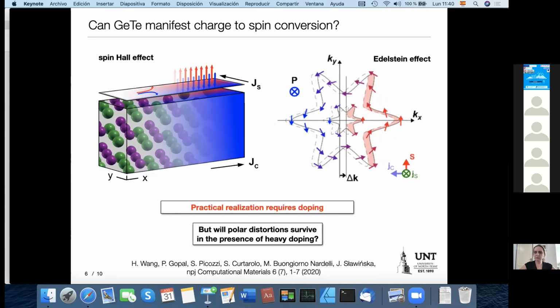Then we try to investigate whether spin to charge conversion could be observed in this material. For example, it has Rashba bands, so it could reveal, in principle, the Rashba-Edelstein effect, or the spin Hall effect, which can occur in any material with a sufficiently large concentration of charge carriers and with large spin orbit coupling.